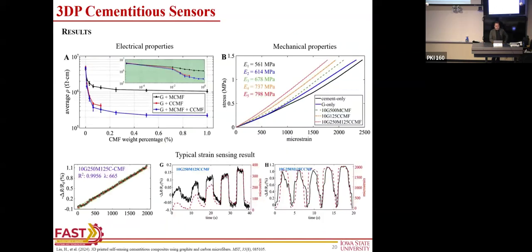So this is what we're after. Try to see if we do have this electrical percolation that exists in sensors that we stamp, right? Once you print them, if they're still holding up, can we achieve percolation? This is not a log plot, so you don't have an S curve, but with a log version, you can see there's like an S type transition. So the sensor needs to be done in that little area. So we did it, it works.